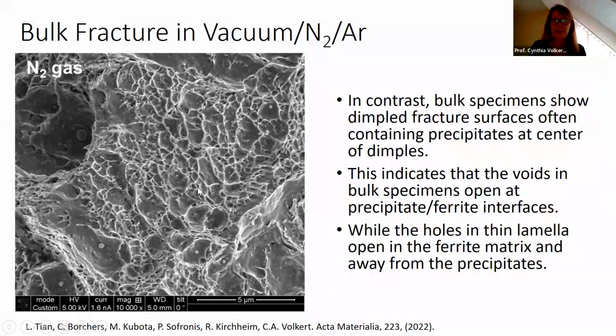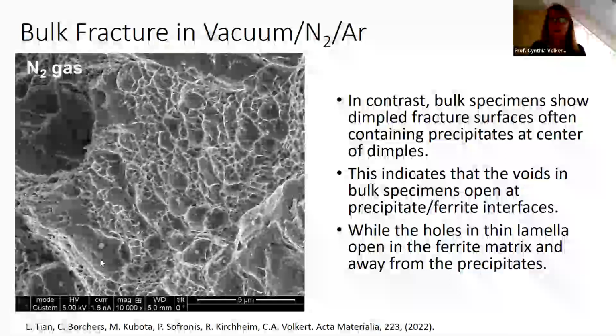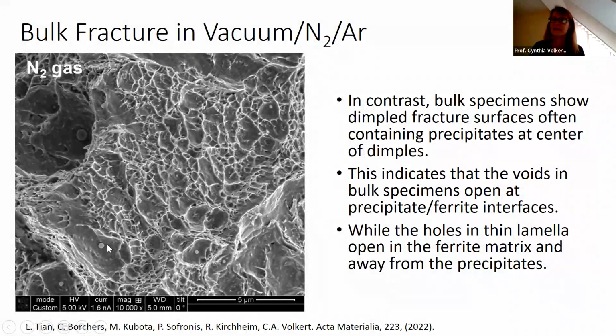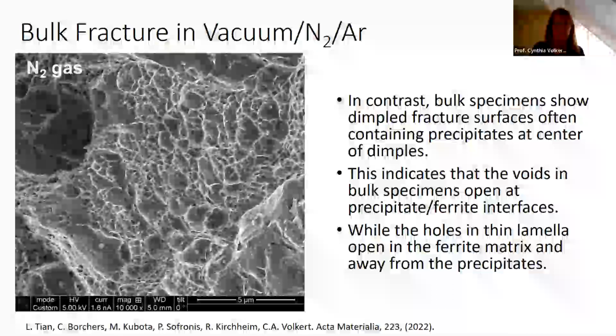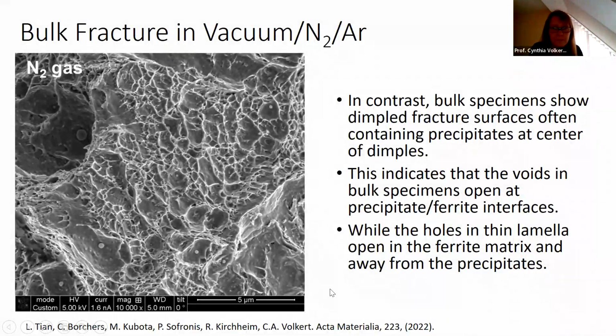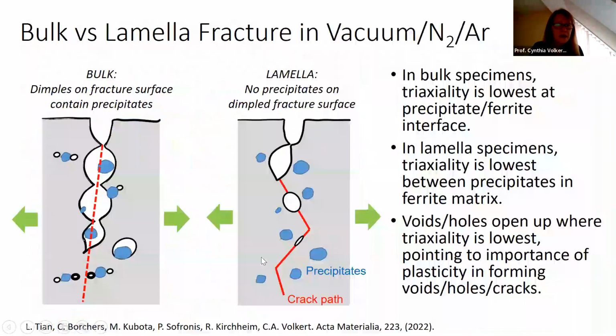It's been concluded that the reason these surfaces contain the precipitates is that the voids open up at the precipitate ferrite interfaces, leaving the precipitates in the fracture surface, as shown here in cross section. And the argument we make here is that the processes in the two cases are quite similar. It's just that the voids open up where the plasticity is highest. Where there's plasticity, you get voids forming. That's usually been assumed to be the case, that plasticity is what's needed in order for a void to form.